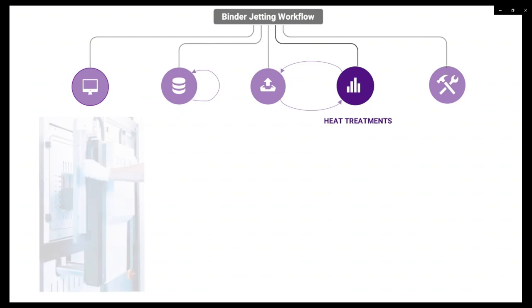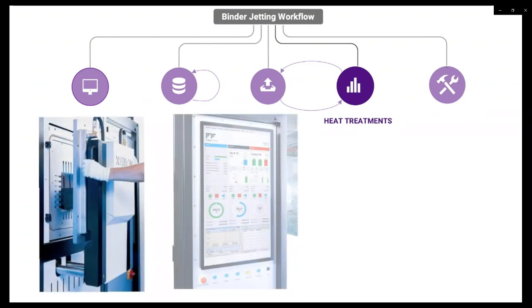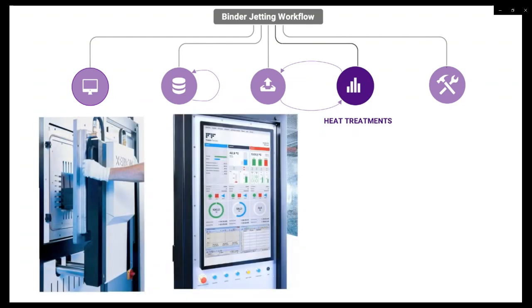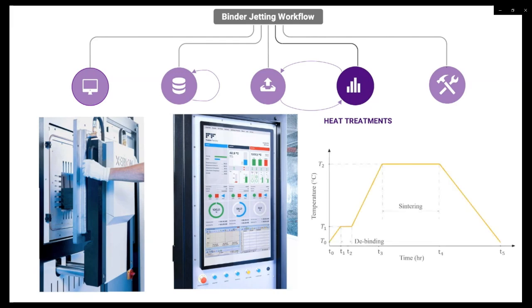The most complex set of steps in the binder jetting workflow are the heat treatments. A heat treatment needs to carefully orchestrate the time sequence of ramp up and ramp down temperatures, as well as the environment gases to achieve controlled part densification with minimal part distortion and desired material properties. Specifically, the sintering process is quite complex if we are interested in customizing both the densification behavior to control the geometric fidelity as well as material properties.